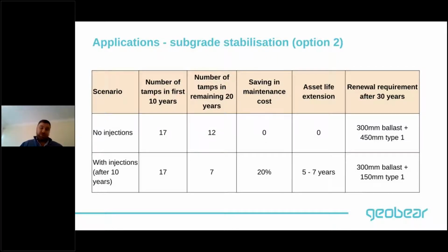And also, because you've reduced the rate of degradation, you've extended the life of the asset by 5 to 7 years. But also, your subgrade is still good, so it's still strong because you treated it with the geopolymer. So your maintenance requirement has actually gone down as well. So from 450 mil of type 1, you would only need 150 mil. So you saved on maintenance, you've extended the life of the asset, but also you've reduced the requirement for future renewals. So you're winning on three fronts here.